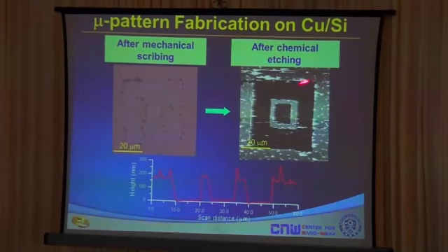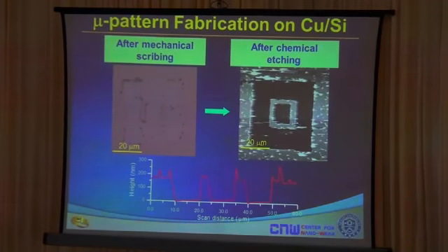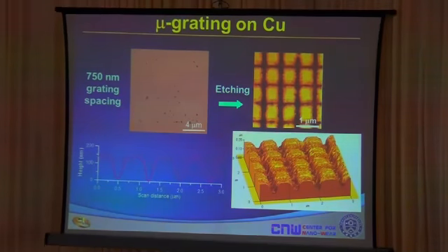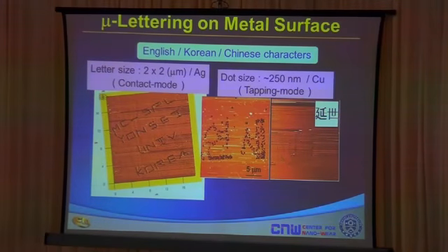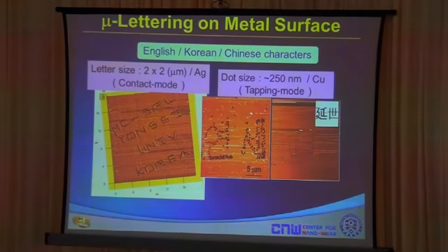You can also create this kind of micro pattern with trenches simply by programming your AFM tip to remove the resist material wherever you want. You create gratings on copper surfaces. You can also use a tapping mode to create these letters in English, Chinese, or Korean by simply programming the motion of an AFM tip. It's a very flexible way of patterning your surface.